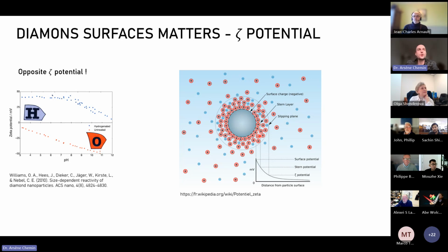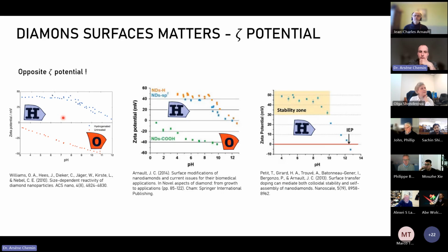And this charge has a huge impact on the colloidal stability of the nanodiamond, for instance, if they aggregate or not. And what was measured already in 2010 by Williams et al. is a very strong difference between hydrogen terminated nanodiamonds that have a positive zeta potential and oxygen terminated nanodiamonds that have a negative zeta potential. And that can be quite surprising, but as we will see, it's actually very understandable from what I just explained before. And this difference between hydrogen and oxygen termination has been observed many times by many groups, and I want to